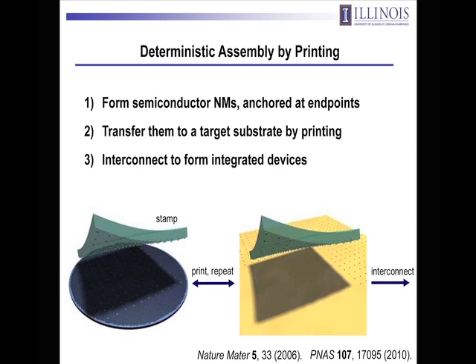Then in a second step, you move the inked stamp over to a target surface, a sheet of plastic, a piece of rubber, and then you print those membranes down. You can come back and, in step and repeat fashion, take a dense collection of silicon or gallium arsenide nanomembranes and spread them out in a desired layout over large areas on a piece of plastic, for example, at room temperature, which is compatible with the low temperature characteristics of the plastic. And so then the next step would be to interconnect those elements to make a functional device. So this is the cartoon illustration of the process.